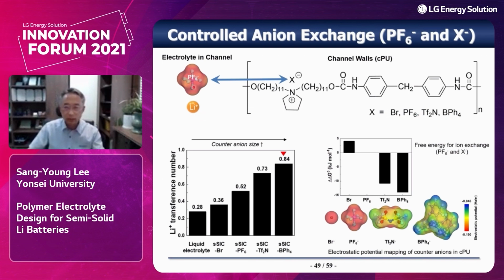And then, as I explained before, the anions from the lithium salt can be exchanged with the anions coming from the cationic polymers. And the interesting one is the anion size in the cationic polymers is increased from the left side to the right side, and then you can see the increase in the cation transference number. That means by controlling the anion size in the cationic polymers, we can adjust the cation transference number in this single ion conducting polymer.